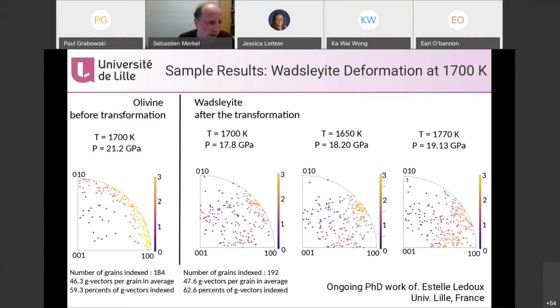And so then we can follow grain orientations in olivine and wadsleyite. What's plotted here is inverse pole figure, and again the dots tell you something about grain orientations. So here I won't walk you through the whole story, but in this case the transformation is reconstructive. We don't have orientation memory between olivine and wadsleyite, and then as we compress wadsleyite, we see the development of lattice preferred orientation, development of texture, which we can then correlate to slip systems and deformation.